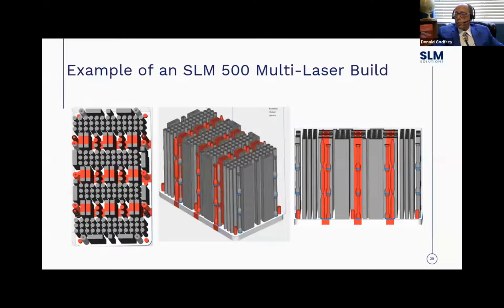And that's a typical one. One of the reasons we like to use the 500 and the 800 machines is because all of these red areas are overlap areas where we're using multiple lasers. So not only are we doing these alloys, but we're comparing single laser printing versus dual laser printing, because SLM really is very, very good with controlling material properties using multi-laser applications.